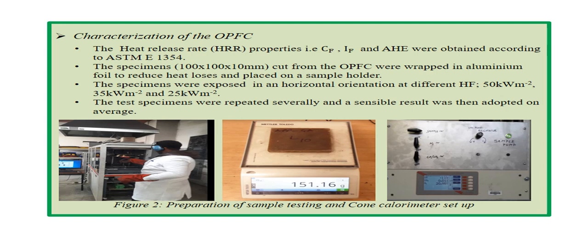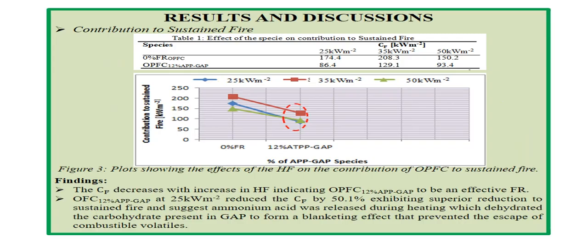The specimens were exposed in a horizontal orientation at heat fluxes of 50, 35, and 25 kilowatts per meter squared. The gas analyzer used is the oxygen consumption as preset on the cone calorimeter apparatus surface panel. The process of obtaining the data was repeated multiple times until a sensible result was obtained for the heat release rate components. Results and discussions obtained.